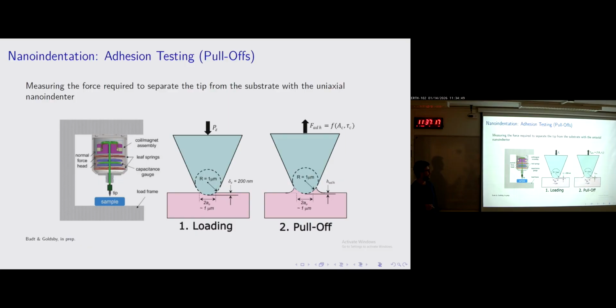And then I unload the whole setup, and I see that when I reach zero load, right, I'm not putting any force on the tip, I need to pull a little bit. I need to go a little bit into the negative side of load and pull on the tip because it's kind of stuck on the sample. It's kind of adhered a little bit to the sample. That's an adhesion test. I can measure this adhesion force. This is the force required to detach or start detaching the tip from the substrate. Of course, this is an exaggeration. It doesn't really look like that. But that's what I'm talking about.